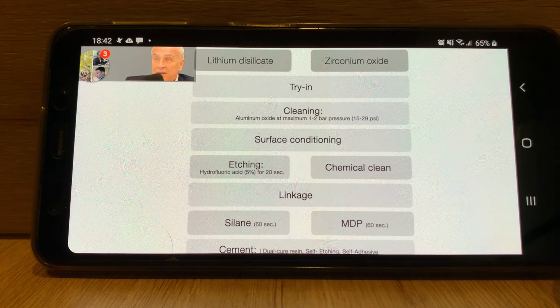Okay. Some companies will make a liquid that has MDP and silane together. They usually also contain metal primer. Okay, we didn't talk about that, even though I said that I might mention it. The protocol for bonding to metal would be the same as zirconium. The only difference is that you need a metal primer instead of the MDP, although that works. And most of these materials have metal primer in them. However, you can get all of these, silane, MDP, metal primer, in separate bottles, and sometimes that's the best way to do them, because once you put everything into one bottle, it tends to lower the quality of these materials.